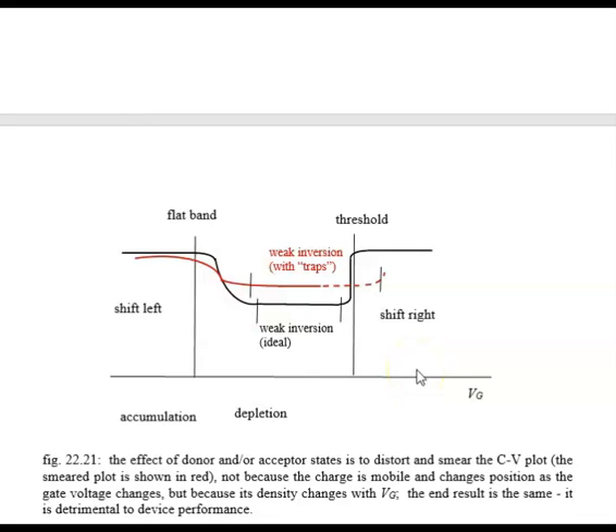What we have with an interface trap charge, we have a shift in the flat band voltage. The flat band voltage shifts from this point to this point, shifts to the left, whereas the threshold voltage, which was over here, shifts to the right. It becomes stretched out. So what that means is, and this is again just for illustrative purposes only, I think you can figure this out.